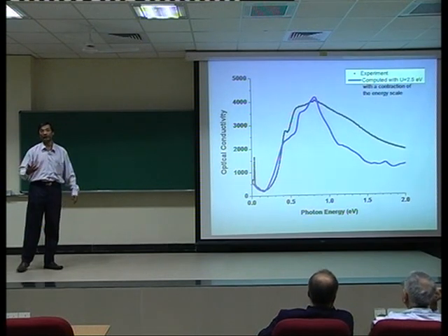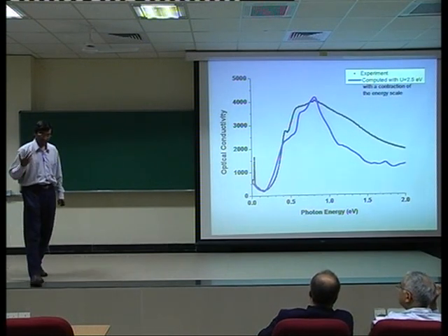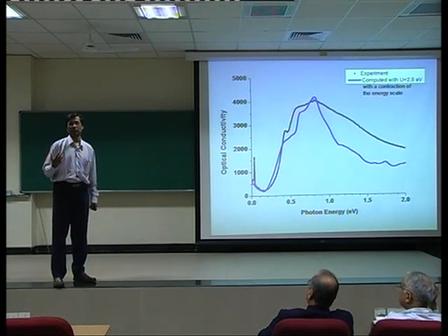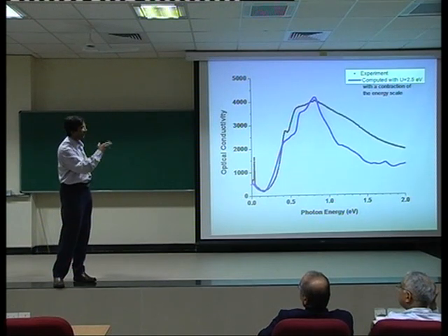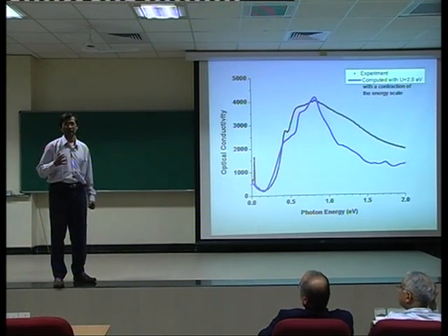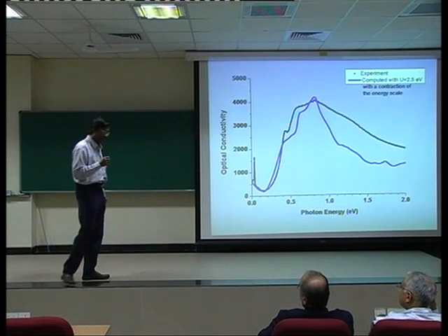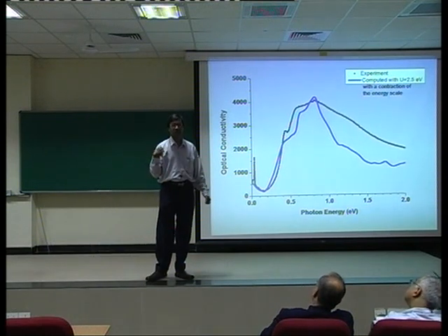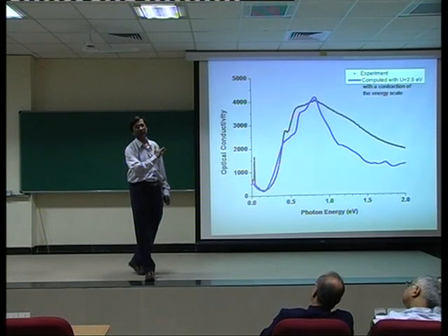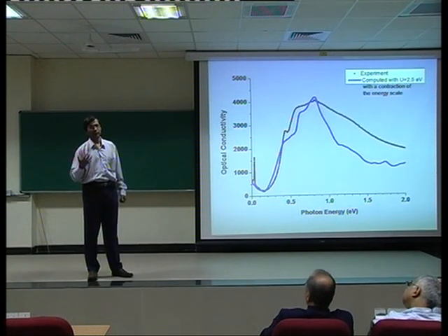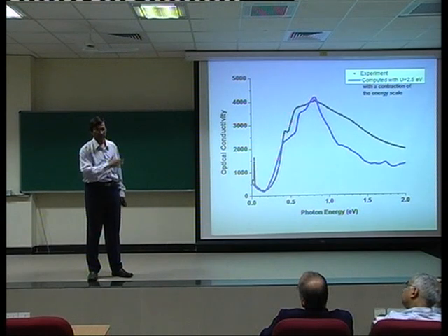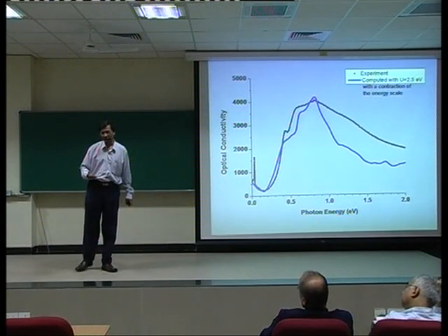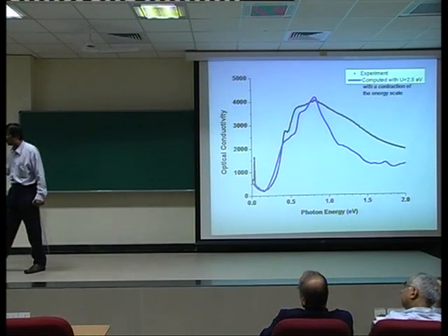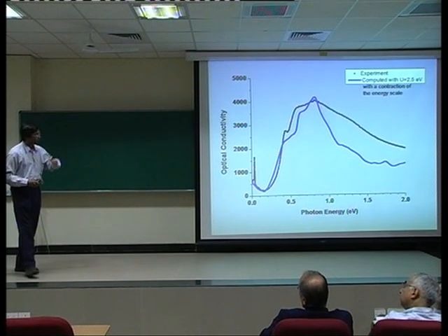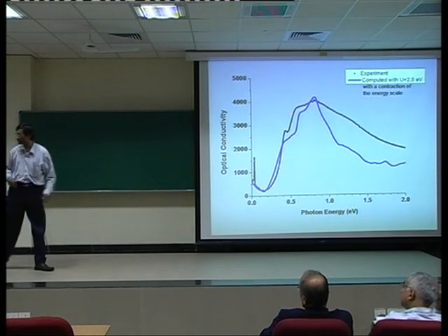We're looking at possibilities of actually avoiding this contraction. There are 2-3 things that potentially contribute to this contraction, and we are looking at some of them. For example, Coulomb interaction effects beyond the kind that we are handling may contribute. We have already seen with DMFT that we actually have a contraction more than what we get from LSDA plus U. We are also looking at whether it is possible to do some kind of excited state calculations. That story is not yet complete, so the jury is still out.